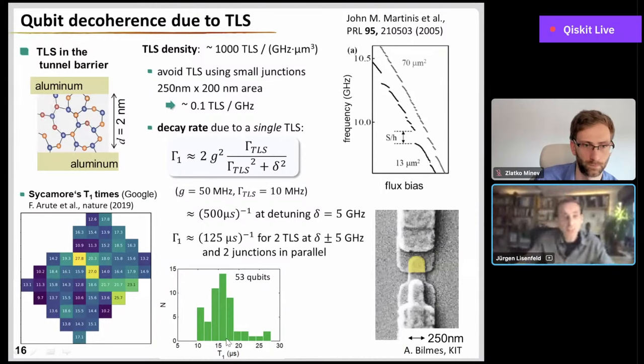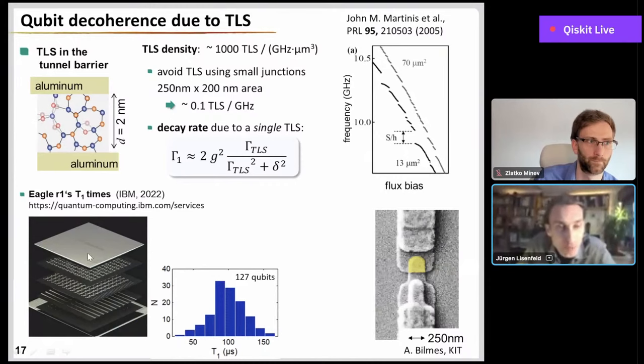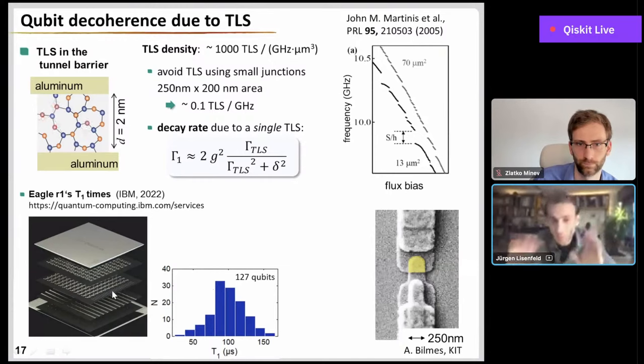And just yesterday, I found the T1 times of the new IBM Eagle processor online. And you also see here this widespread distribution. But it's very nice to see that the average T1 time is now, even in this upscaled version, much better than before. So 100 microseconds is a very promising number, I would say. But still, of course, you have this plus minus 50% total width of this distribution here, which is most likely just given by these random occurrences of defect resonance frequencies in each junction.